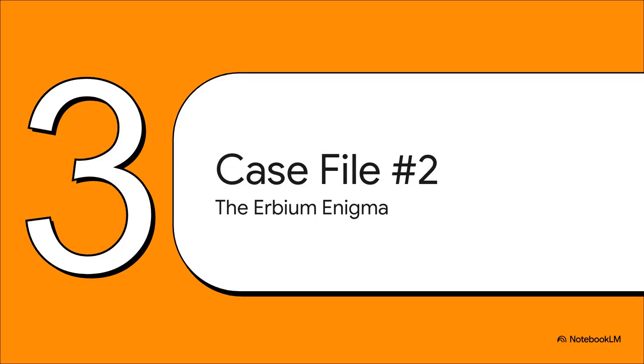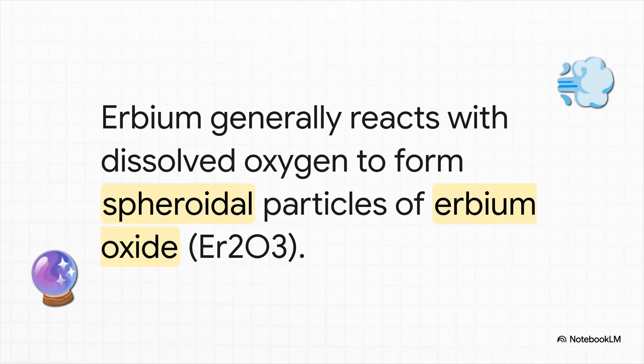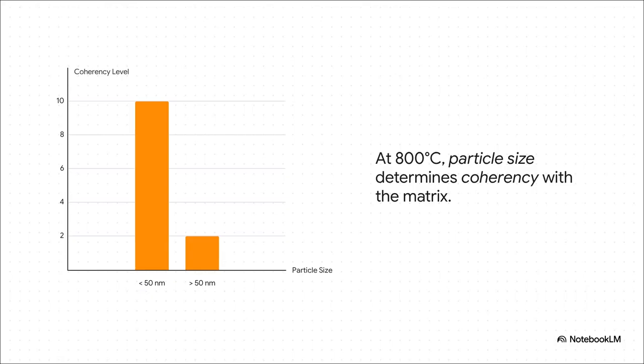Okay, now let's move on to our second case file and see what's going on there. The erbium enigma. And trust me, this story has a pretty surprising twist. So when you add erbium, it does its thing, scavenging oxygen and forming these cute little spherical particles of erbium oxide. Seems nice and simple, right? Well, not so fast. The first little wrinkle they found had to do with size. At 800 degrees Celsius, the really tiny particles, we're talking smaller than 50 nanometers, were coherent. They fit in great. But as soon as they grew bigger than that, they became incoherent. Their atomic structure just didn't line up anymore.